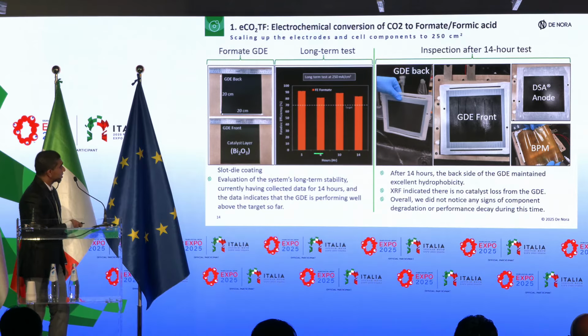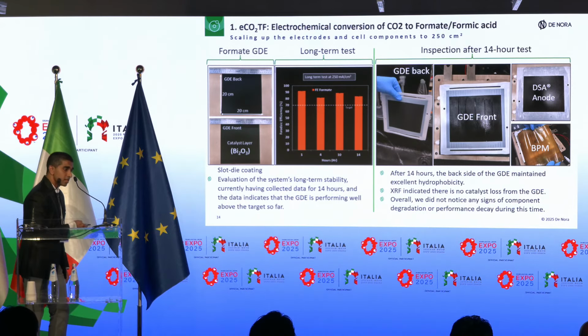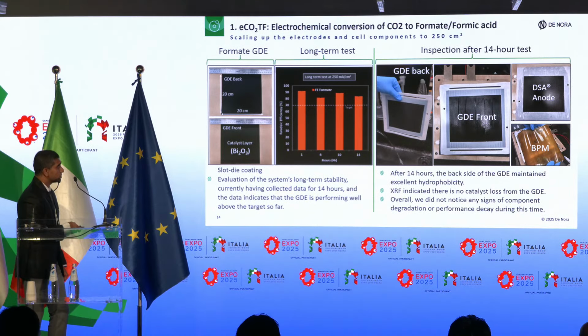What you see here is part of the long-term test results. After 14 hours, we also hose down the backside of the gas diffusion electrode. There is actually a video, it's not playing for some reason. But when we hose down the backside of the electrode, we can see water is bouncing off. That means it's maintaining good hydrophobicity. We also noticed there is no major degradation of the catalyst or any other component of the system.